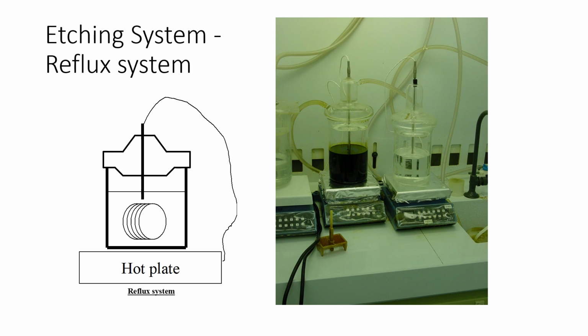Wet silicon etch is typically conducted in reflux chemical baths like this. A typical reflux system is a glass jar where wafers are placed inside with good circulation. There is a cooled top on top so that the evaporated liquid would drain back into the solution in order not to change the concentration of the solution. You can use EDP or you can use KOH, potassium hydroxide or ethylene diamine pyrocatechol.